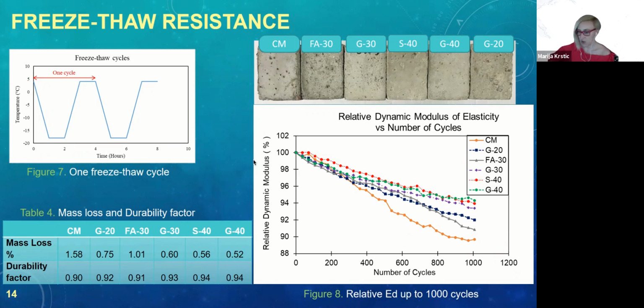All these samples, as you can see on this image here, showed very small deterioration. Specifically, S40 and G40 showed almost no deterioration. And that can also be seen here in this graph of relative dynamic modulus versus number of cycles.